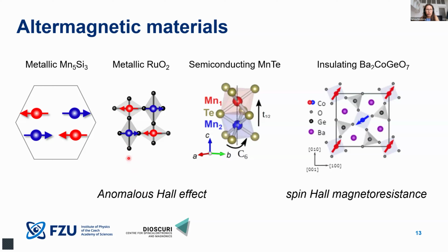And probably the model, or the best known structure or cartoon, is this d-wave system, these ruthenium dioxide related materials, where the magnetic atoms are surrounded by oxygen cages, and then one can see that by flipping this arrow, one cannot simply recover the original image by translation or inversion. So there is a rotation of the crystal lattice needed. Therefore, this is probably the best-known way to get the altermagnetic symmetry.